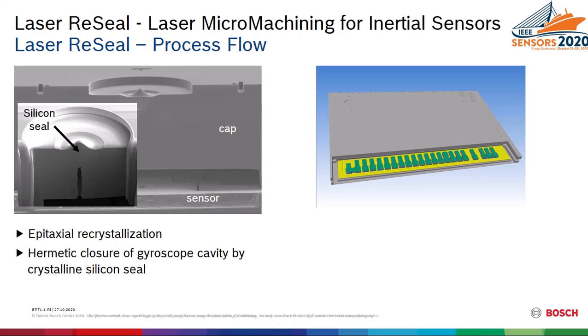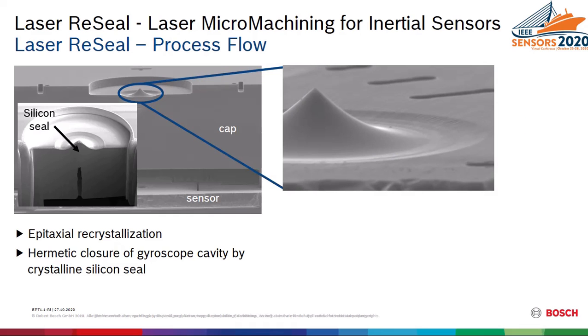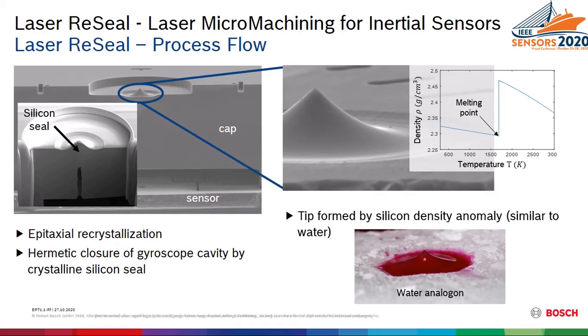And if you take a closer look, you see that there's a tip, and you might ask, where does it come from? So the reason is that silicon has the same density abnormality as water. So the liquid silicon has a higher density than the solid silicon. And when the melt pool crystallizes, it will push out the tip. This is an example in colored liquid in ice, and you see also the formation of the tip.